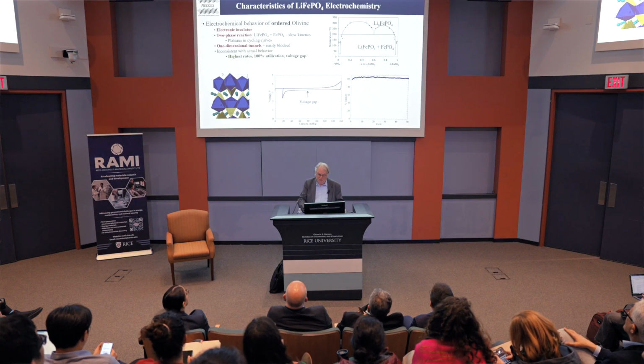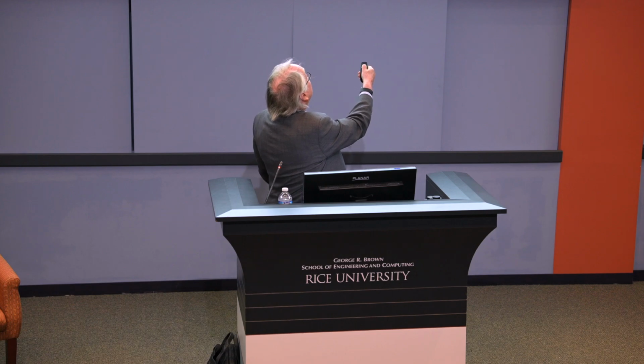So the trick in all this is, how do you make it work? It turns out you make it work by using small particles. So typically, if you're using lithium iron phosphate, it's about 50 nanometers. So the electrons can get in and out, and you use quite a bit of carbon to give conductivity to the particles, and you substitute other elements into the structure, which then reduces this line to about down here.